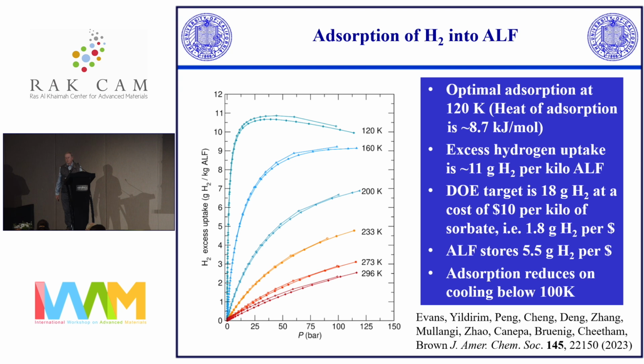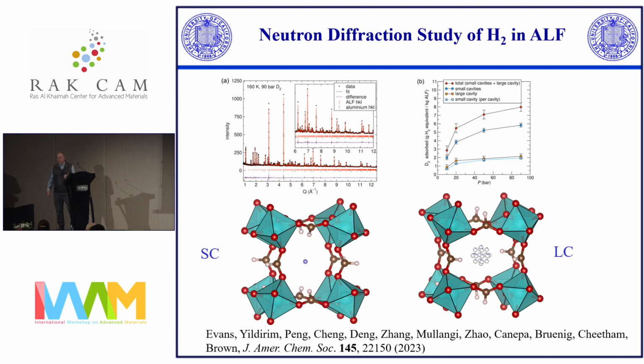So this was published in JACS just before Christmas, and we've done neutron diffraction work on the location of hydrogen. So it's very localized in the small cavity, a bit like the CO2 was earlier, but in the large cavity it's delocalized quite a lot away from the center, but we can model that quite well, and we've followed the uptake of hydrogen as a function of pressure and compared that with our adsorption isotherms. And again, the neutron work that Hayden Evans did is absolutely stunning.